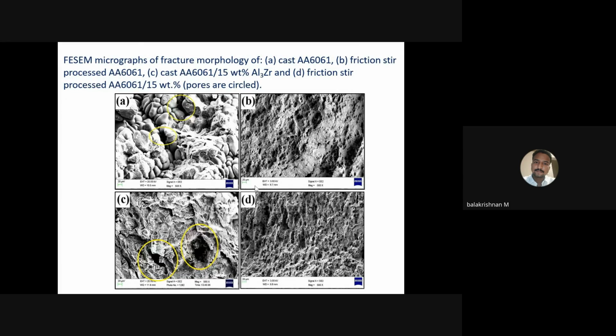Here during the tensile test, we can observe some pores in the Al3ZR particles. This is due to the sudden solidification and the entrapment of gases and displacement of particles. That's why it happened. After friction stir processing, it was completely removed.